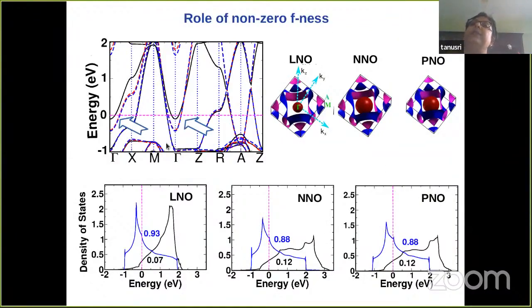And this is the calculated band structure, but now of the three compounds, the lanthanum compound, neodymium and praseodymium. The band structures of neodymium and praseodymium turned out to be rather similar, with the size of this electron pocket at the gamma point being very similar. While for lanthanum, as mentioned already, the electron pocket diminishes at the gamma point quite a bit. And this is also seen in the two-band density of states of these three compounds, the blue one being the density of states coming from the nickel x² minus y², and the black one from the axial orbital. The zero of the energy, as usual, is set at the Fermi level, and the weight below the Fermi level of this axial orbital for praseodymium and neodymium is about 12%, while in the case of lanthanum, it is reduced to 7%.